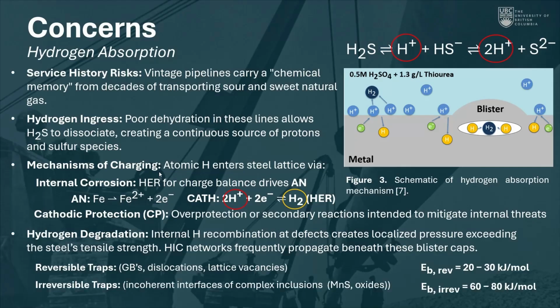And so I did want to just briefly mention that there are two trap sites where hydrogen can accumulate, those being reversible and irreversible traps. So reversible traps refer to fast diffusion pathways like grain boundaries, dislocations, or lattice vacancies, and they have a much lower trap binding energy compared to irreversible traps where, if you think of a highway and you have cars and then there's a sudden crash on that highway, then you start to have a much slower flow of traffic. And that's exactly what irreversible traps are.